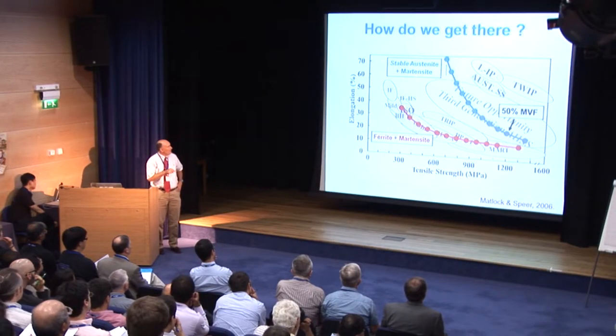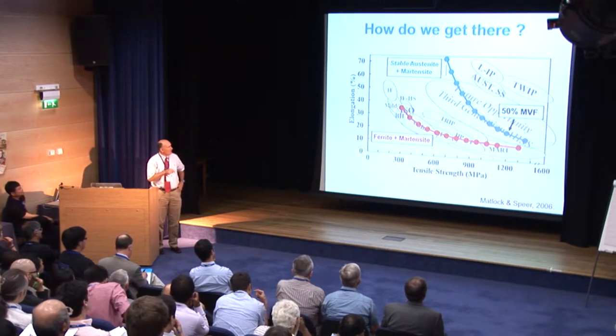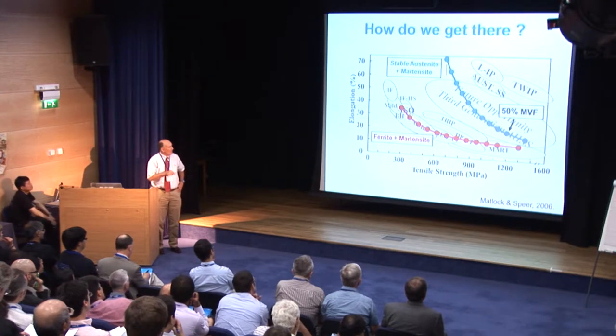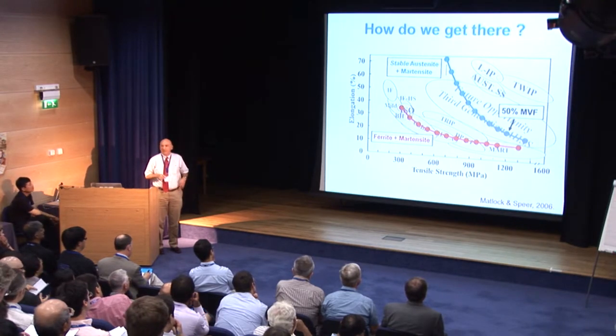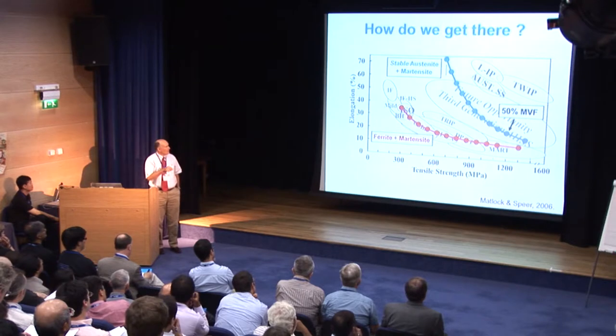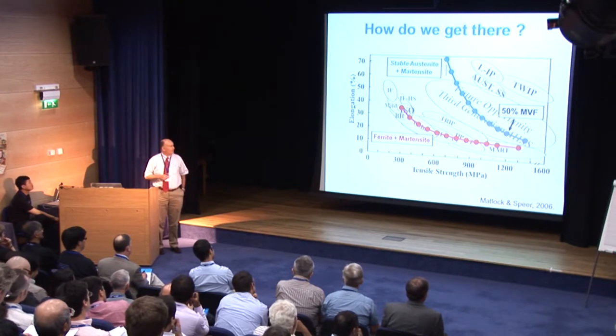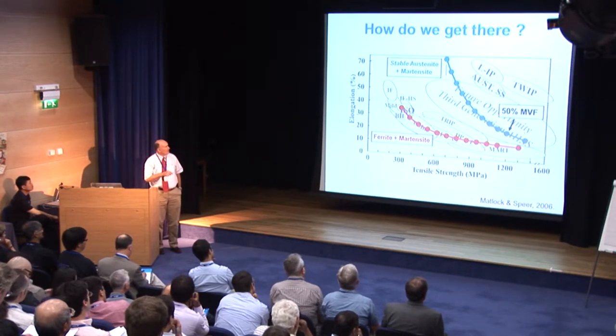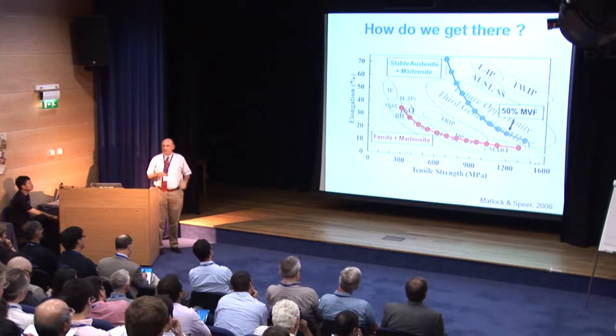If instead we look at combinations of a particular stable austenite mixed with martensite, we get much better strength-ductility combinations in this future need area of steels. And actually, instead of using stable austenite, we can control the austenite stability. I don't think we really know how to tune the austenite stability in practice as well as we would like to, but we can move this curve around as well, and so it's a very interesting opportunity.